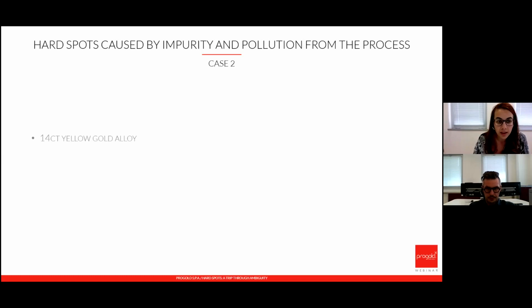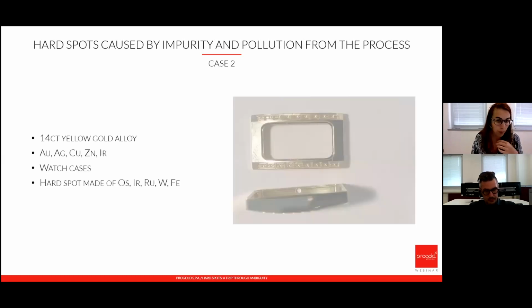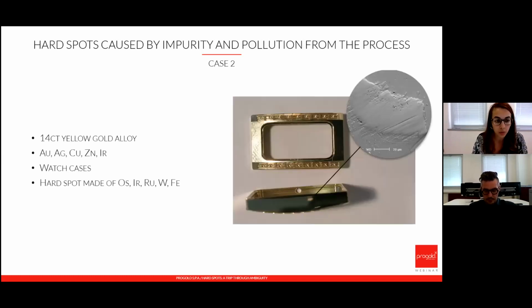Here you have an example in which we have both the first and the second case. We have here osmium, iridium, and ruthenium, which means we have contamination from the gold. But as you can see, we also have iron and tungsten. These were cases processed with CNC tools, and the scraps remaining at the end of the process were being reused, and the scraps were contaminated. So we were actually inserting residuals of the tools inside a new alloy.